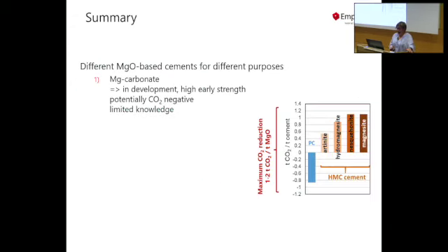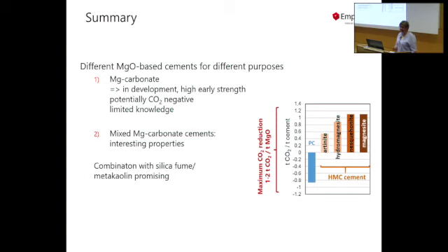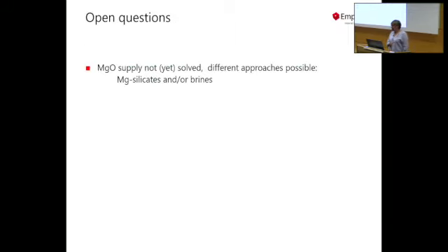So maybe to summarize the magnesium oxide part: we can make magnesium carbonate cement. They have a relatively high early strength. They are potentially CO2 negative. We still have a lot of open questions. We can look at mixed magnesium carbonate cements with silica and metakaolin, and they seem to be very promising, but there are also many open questions.